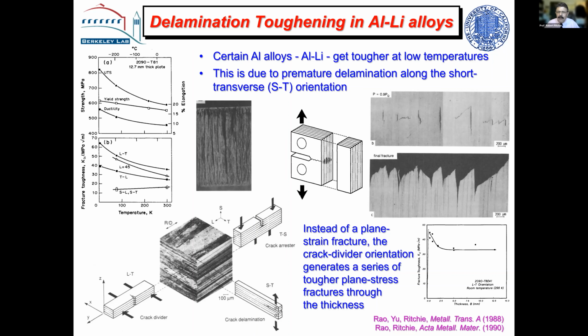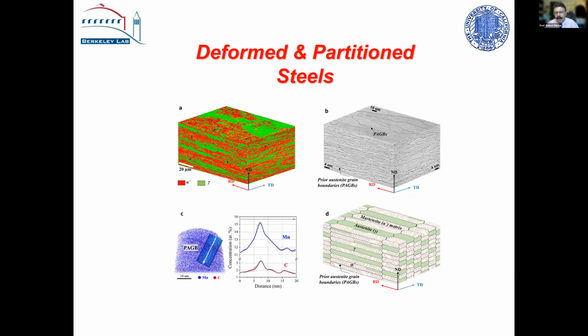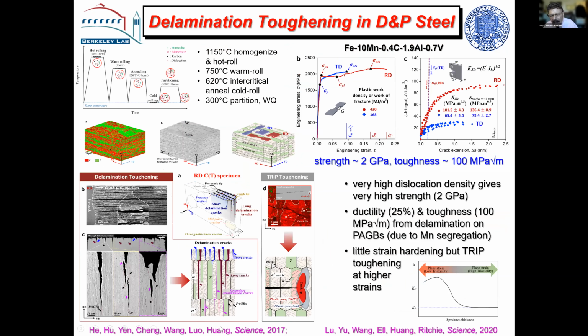Well, when we look at these new materials, for steels, a similar thing happened. These are called deformed and partitioned steels, and they were developed by Mingxi Huang at the University of Hong Kong. And his philosophy here was to make a very cheap steel with great properties. And this is cheap. It's got just manganese in, a little bit of carbon, a little bit of vanadium, a little bit of aluminum, but mainly a 10 manganese steel, very cheap. And he takes it through a very complicated series of heat treatments involving hot rolling and warm rolling and annealing. That's the difficulty, I think.